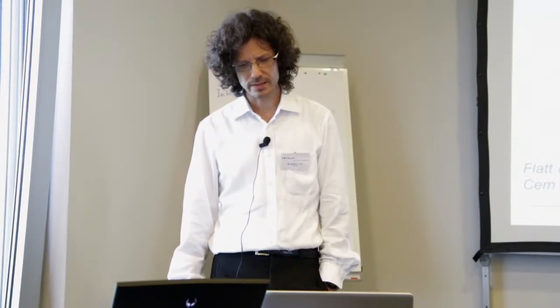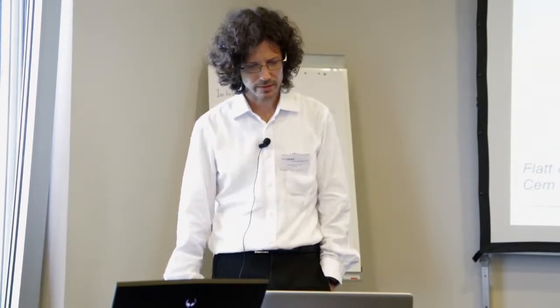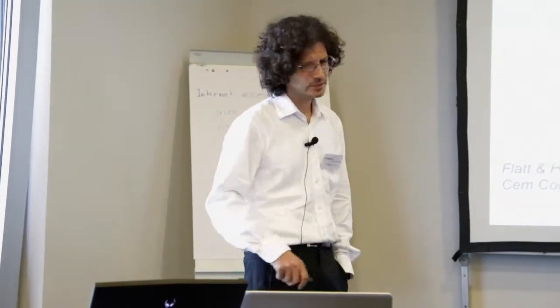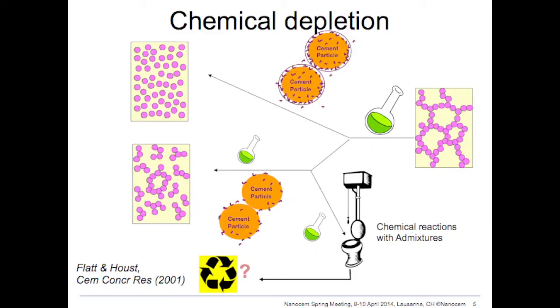And the concept is that if in one way or another you lose part of the admixture, the degree of surface coverage is reduced, and this leads to some degree of flocculation in the system, which means that the fluidity of your material will be impaired. And the question that the Nanocem project addressed is: is there such a waste product? What is it? What can we learn about it to try and prevent it from forming?